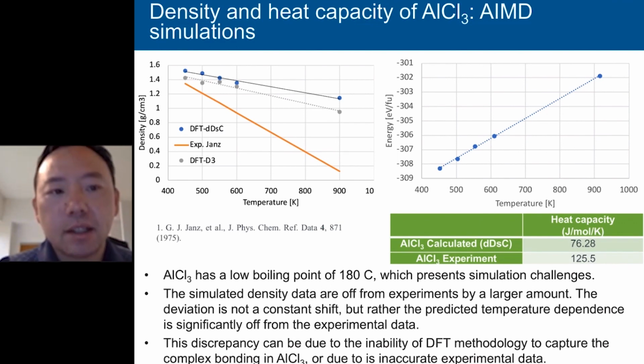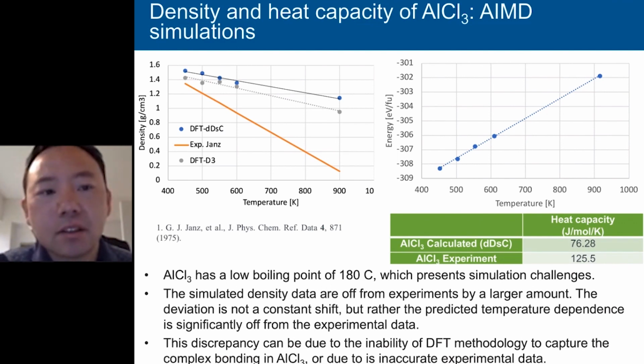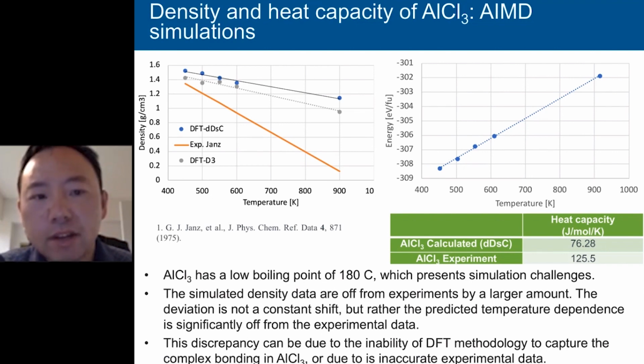This slide shows another interesting application, to aluminum chloride. Aluminum chloride is a very interesting material in that it has a very low boiling point of 180 degrees Celsius. This low boiling point gives us some computational challenges. If you look at the left figure, you can see that the Ab-Initio calculated density data are very far from the experimental data by a very large amount. Also, the slope is not a constant shift. So essentially the modeling and experiments have some large discrepancy.